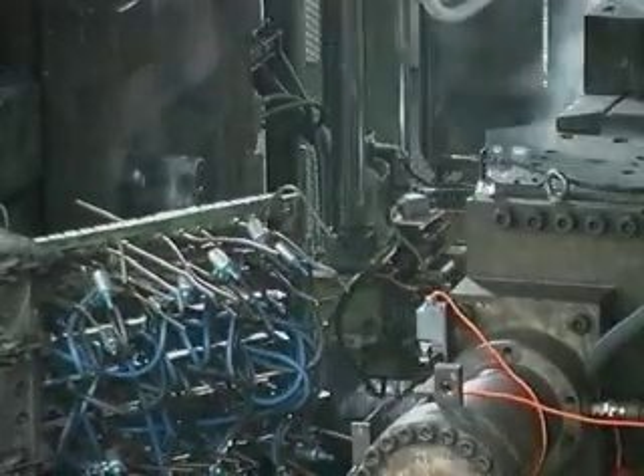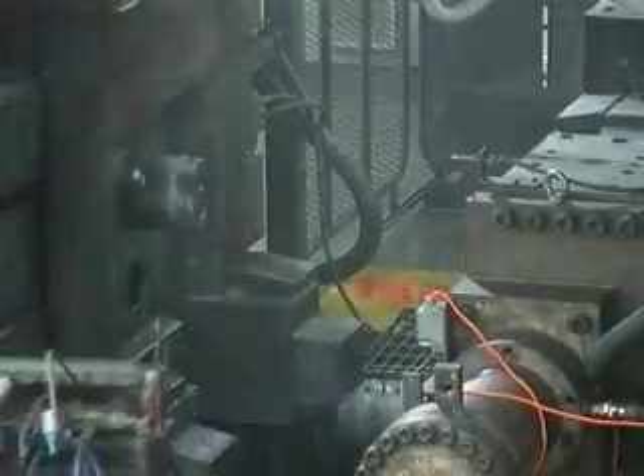The die opens and an actuated arm removes the casting from the die. The die cavity and metal cores are drenched with a water-based die spray to selectively cool and lubricate parts of the die and help extend die life to 150,000 shots or more. This machine has a clamping force of 2,250 tonne, and the machine's cycle time is 90 seconds. The cost of a machine of this size is $4.5 million, a large investment that must be repaid with high productivity.